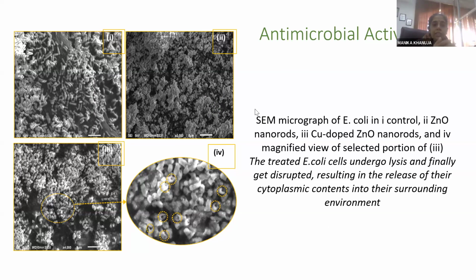If you look at these images, this first image is E. coli intact. This image we have taken in our paper only. And then when we interacted with the zinc oxide based materials and copper based materials, you can see cell lysis. The whole cytoplasmic content has come out. So, dead mass. These same micrographs are also helpful. Sample preparation was specifically done for these materials and conditions, and the antimicrobial activity or cytoplasmic killing part is done. Very good image. This work is published in Journal of Nanoparticle Research by us in 2017.